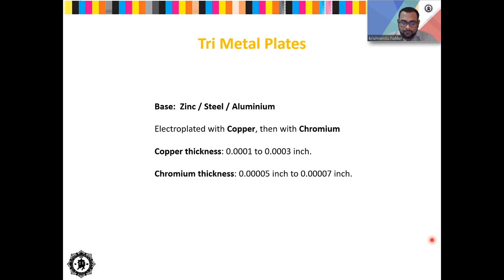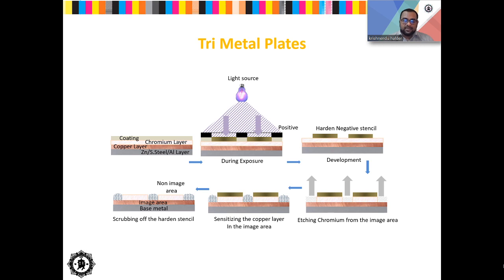Generally for trimetal plates, we have seen that the copper layer thickness ranges between 0.0001 to 0.0003 inch, and for the case of your chromium thickness as your non-image metal, it is 0.00005 inch to 0.00007 inch. So it's a very thin layer of your non-image metal as well as a very thin layer of your image metal that has been electroplated over the base metal. Now this is the schematic diagram. So the process of these trimetal plates is more or less the same as the process of your bimetal plate making.